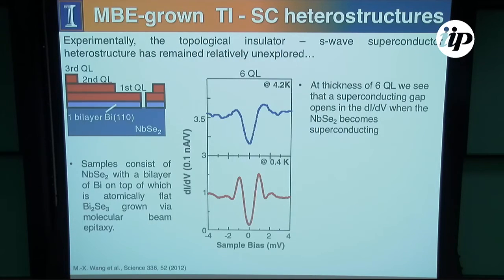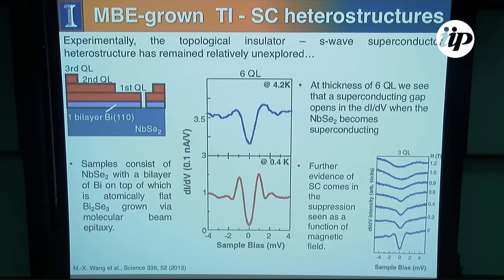But sometimes they're successful, and when they are, then you can see that for 6 quintuple layer systems at 4.2 Kelvin, you can see that they start developing a superconducting gap in these thin films of bismuth selenide. And this is just because, of course, as you cool down, niobium selenide becomes superconducting. And eventually you can see this is evidence of superconductivity because you apply a perpendicular magnetic field to kill off the superconductivity. And so as you increase the magnetic field here for a 3 quintuple layer system, you see that the gap starts to close. Okay, so this is good things.